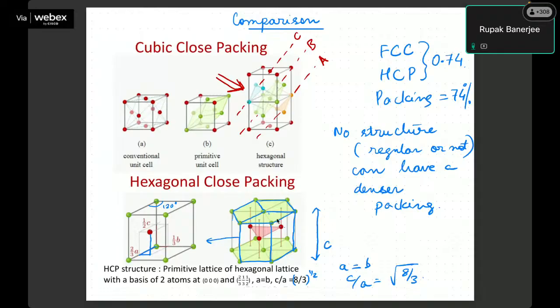Because you need two basis points. So when you take this section out, this is how this section looks. This section has this basal plane A and B, and there is another atom which is sitting somewhere here. Now this atom sits at a position which is 2/3 of A, 1/3 of B, and half of C. So with respect to this, it is 2/3 of A, 1/3 of B, and half of C. 2/3, 1/3, and half. So here you will see 2/3, 1/3, 1/2.